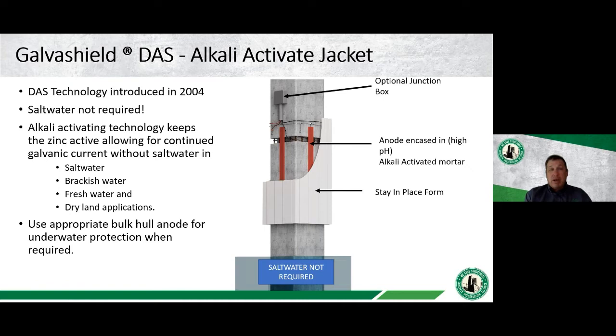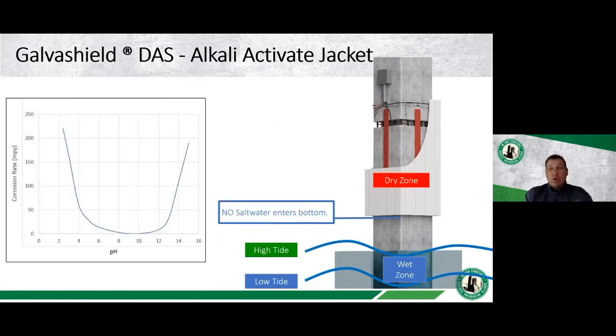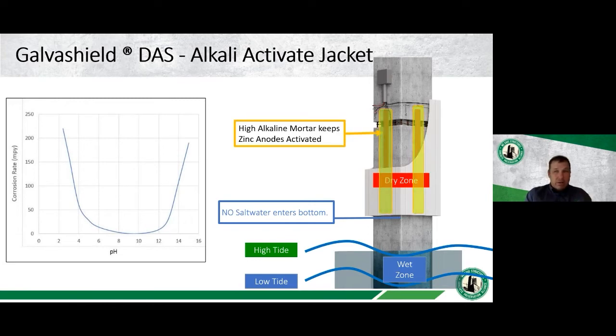Sometimes there may be an application where you will still want to use a bulk zinc anode. It would still be attached below this jacket if you were using it in that wet zone or submerged zone. So we don't have the salt water. Salt water is not entering the bottom. We have our zinc anodes embedded in that high alkaline, high pH mortar, right? We know that high pH keeps the zinc in an active state, and that's how we have the anodes providing this galvanic current.